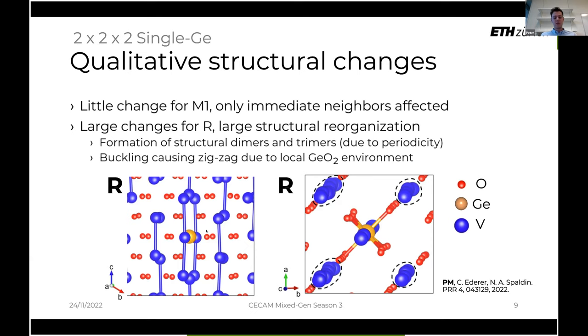But the qualitative conclusions from this can be drawn because also if you look along the chain, so now this is looking down along the vanadiums, which were previously in this rutile phase very nicely ordered in a spatially regular fashion, now we see in these dashed ellipses that we get some sort of caterpillar-like pattern with these vanadiums being tilted off axis. And if you remember back to the first few slides and to Silke's talk, the difference between the rutile and the monoclinic structures is indeed that in the monoclinic structure, we have dimers forming and we have tilted vanadiums existing. And so in some sense, we qualitatively observe some change from the rutile in the direction of the monoclinic. But we, of course, want to make this more quantitative.